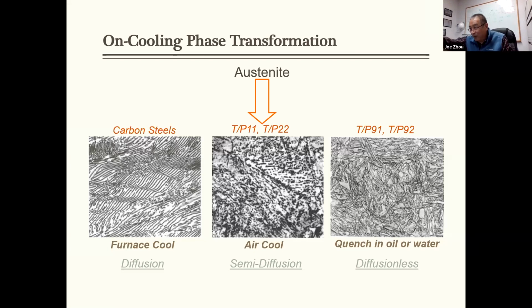But for the bainite structure, it's semi-diffusive, so 50% of the precipitate is already coming when bainite forms. The other 50% are still waiting to come. You can use controlled tempering to bring the other 50% out as designed. So you can put whatever precipitate into certain locations, control their size, control their interface structure.